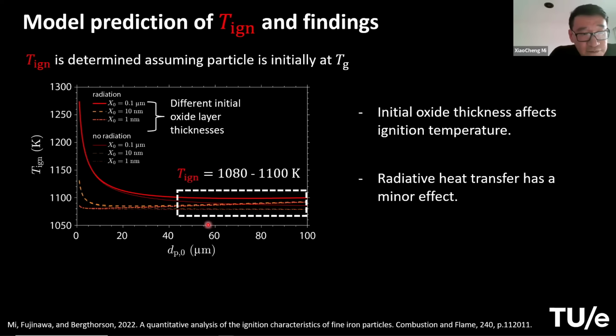So you see for large enough particles, in this range from 50 to 100 micron, which is the typical particle size range that we use for larger scale combustors. In this range, you see that the ignition temperature is around 1080 to 1100, right? And in these cases, we assume that the particle's initial temperature is the same as the gas temperature. So if the particle is injected into the chamber at room temperature, it would require a higher ignition temperature, which I'm going to show later in the slide.